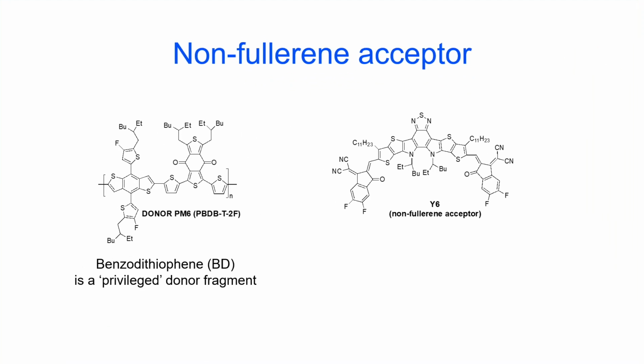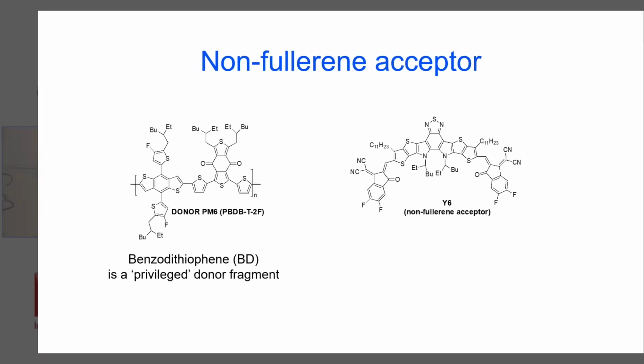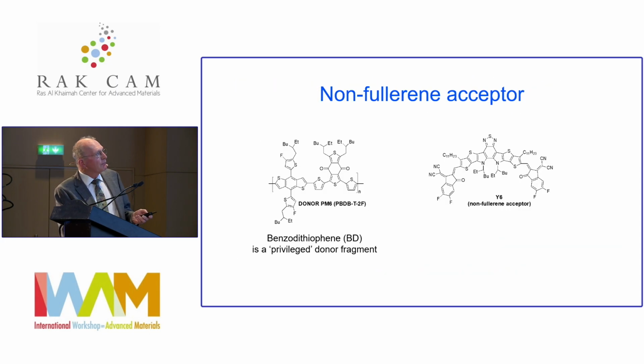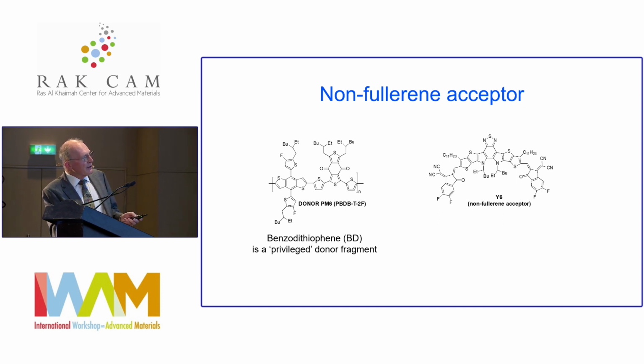And on the left I've drawn what's become, just as we talk about privileged catalysts in catalysis, a privileged functional group for the charge donor, the polymer donor group, which is capable of storing positive charge. And this privileged group, benzodithiophene. So typically you see benzodithiophene and then thiophene rings with various substitution patterns. That is a really core group which has given high open circuit voltages.